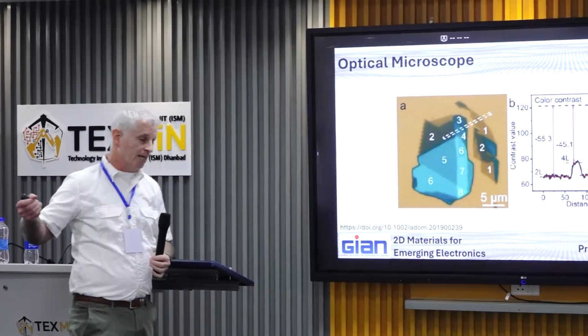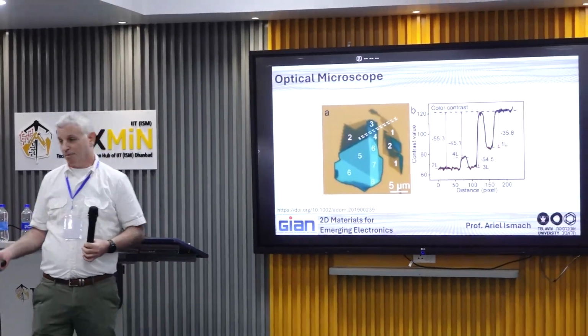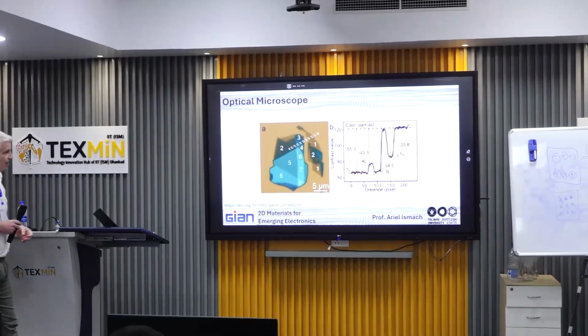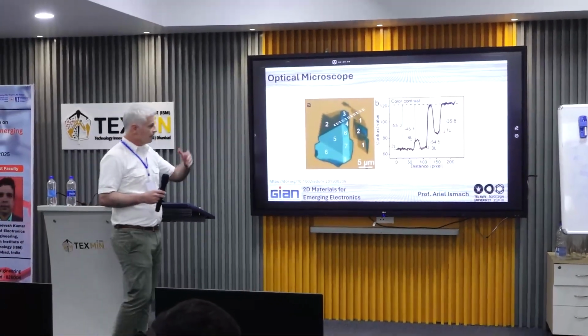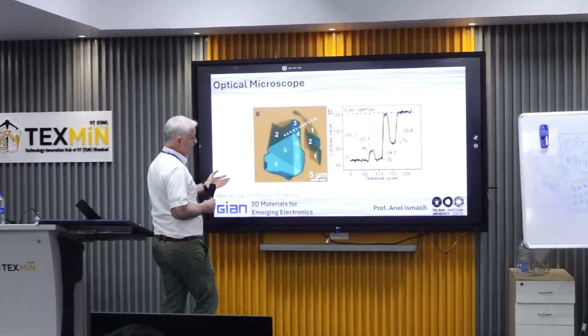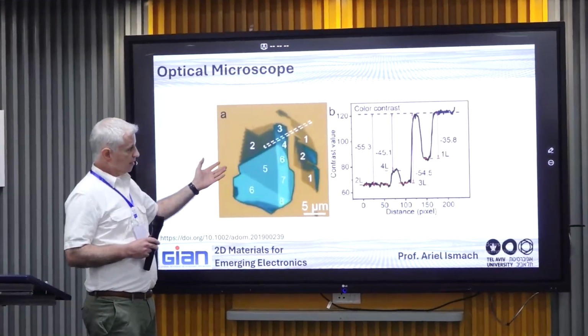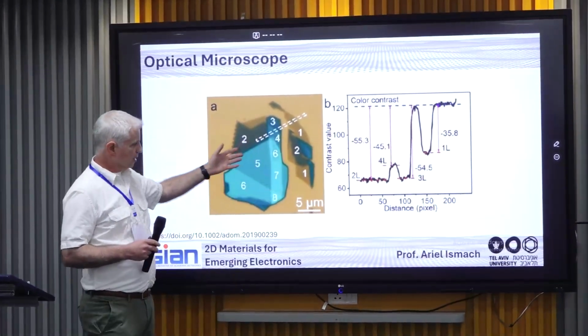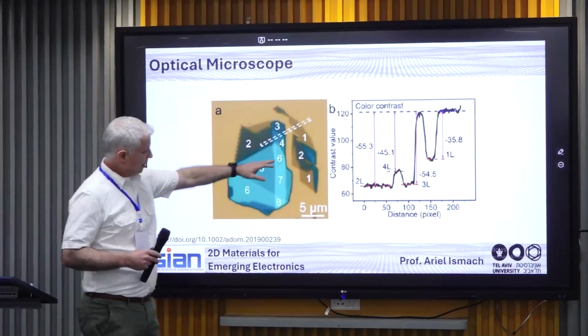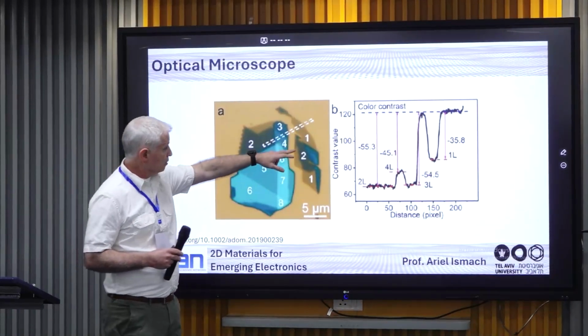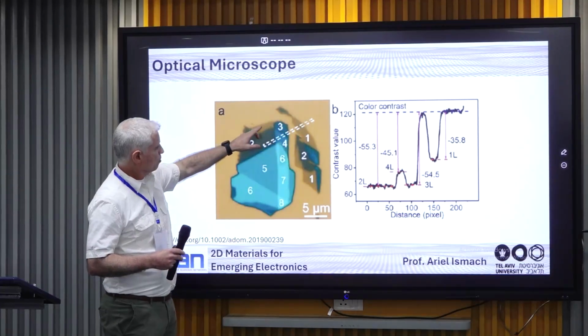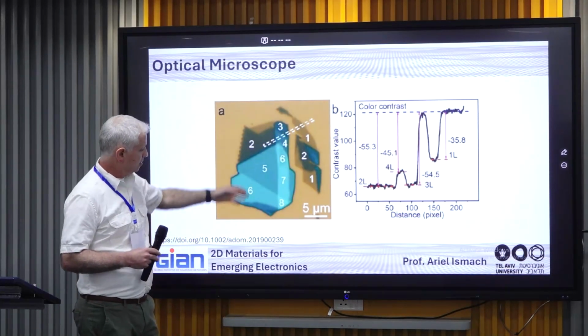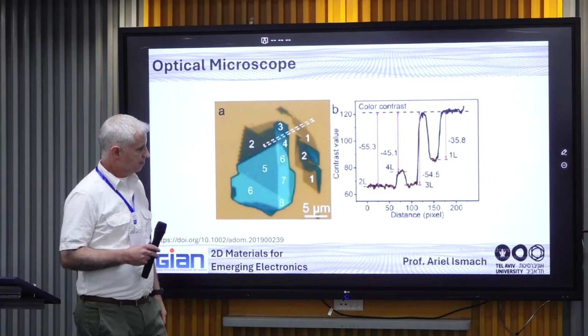As you can see here, an example of a flake, of course, by exfoliation. Usually, when you exfoliate the material, you get many flakes on the substrate with many different numbers of layers, which in this case is very convenient because then you can show all together. So you see that at the edges of the exfoliated flake, you can localize single layers, and then you have thicker layers.